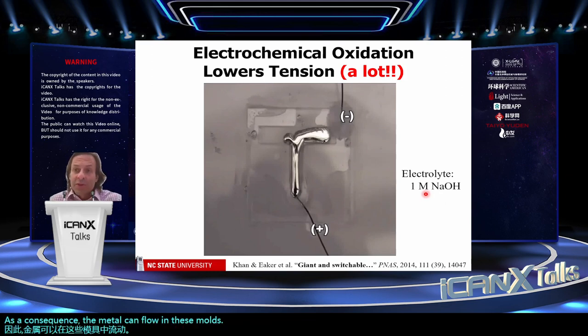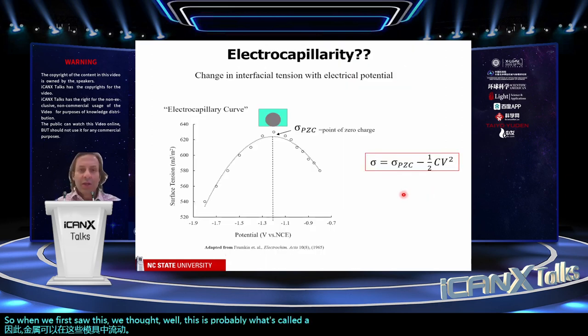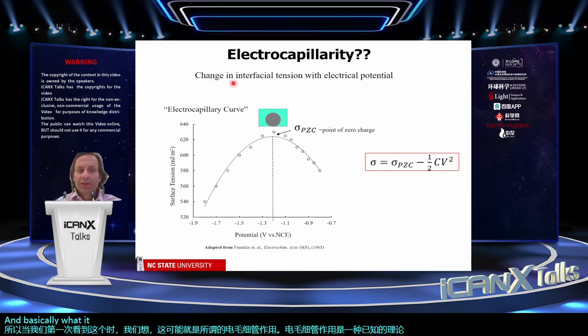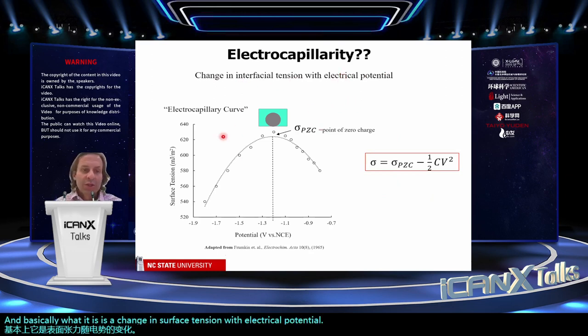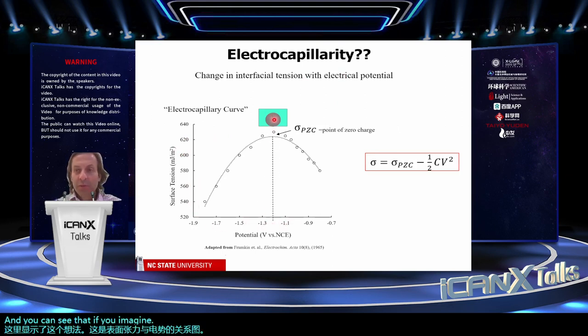So when we first saw this, we thought, well, this is probably what's called electrocapillarity. Electrocapillarity is a theory that's been known since the late 1800s. And basically what it is is a change in surface tension with electrical potential. And the idea is shown here. This is a plot of surface tension versus potential. And you can see that imagine this is your liquid metal droplet inside of an electrolyte. And if you don't do anything, the surface tension is very large, like 600. That's almost 10 times that of water.